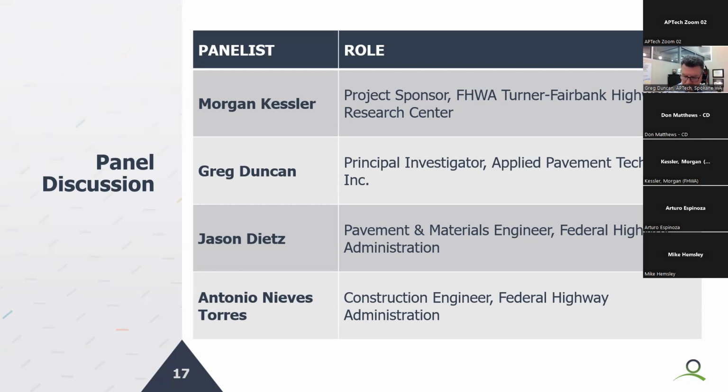In that, we found that it did fine all the way through the tests, except for the multi-layer loaded wheel, which was TP 147. We weren't expecting that, so we went back through and we saw that the asphalt, even though it broke down, we had to crush it. So it broke down through that crushing like we would have expected it to for a harder pen asphalt. The pen was right there on the borderline of where I would have said that we would have seen insignificant effects from it, but it was right there on that borderline. So it was in that high range.